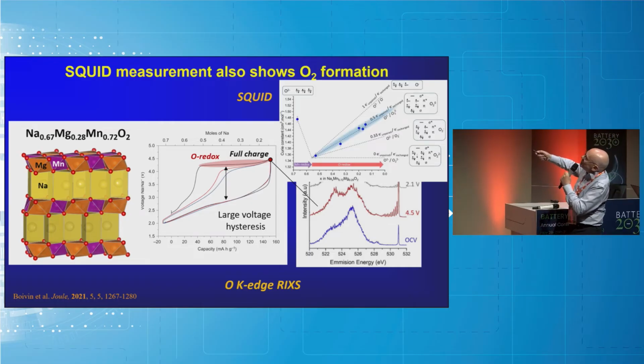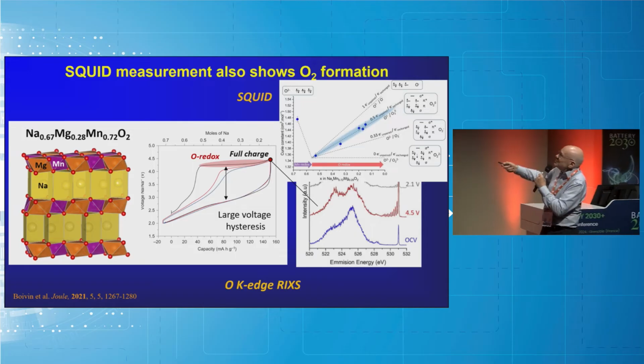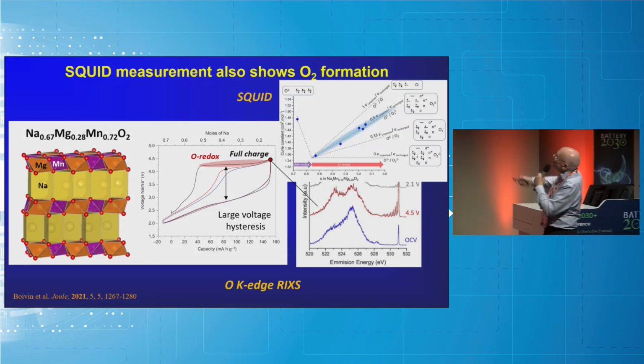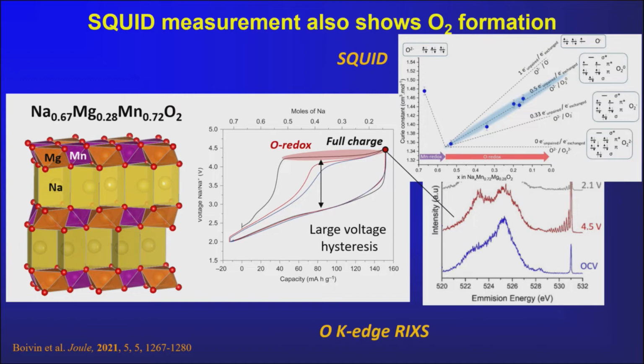This is a plot of the Curie constant on the y-axis as you extract sodium from this material. So the initial change, this bit in purple here, is just the oxidation of a little bit of manganese 3 because this is 0.28, 0.72. From then on, there's the experimental change in the Curie constant, those dark blue dots that you see here.